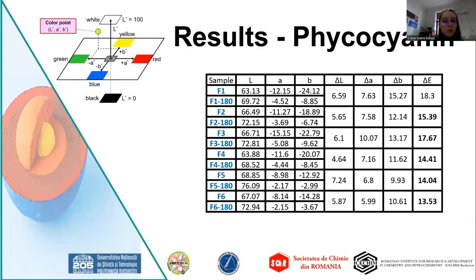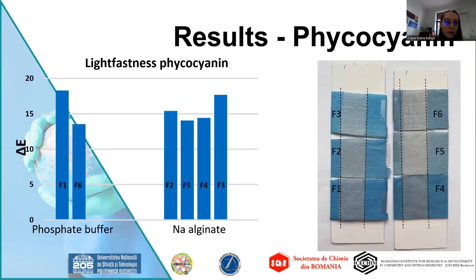The results of the Xenotest were observed regarding the CIELAB coordinates. As we can see here, for phycocyanin, delta E, which is actually the observed hue difference between time 0 and 180 minutes, has values of over 14 in almost all cases, which means the natural dye has a poor light fastness. Here, the differences can be better observed.